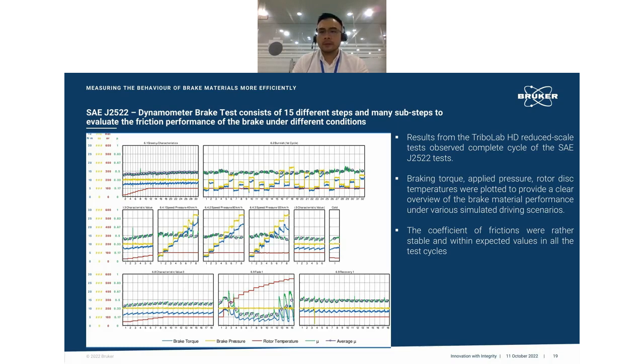So from the results of the TriboLab HD reduced scale test, we observe a complete cycle of the SAE J2522 test. On the axis on the left, the braking torque, applied pressure, and rotor disc temperatures were plotted to provide a clear overview of the brake material performance under various simulated driving scenarios. In general, if I look at this plot, the coefficient of friction was rather stable and within expected values in all the test cycles.